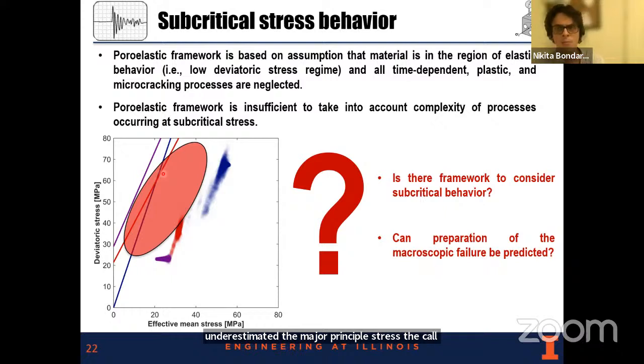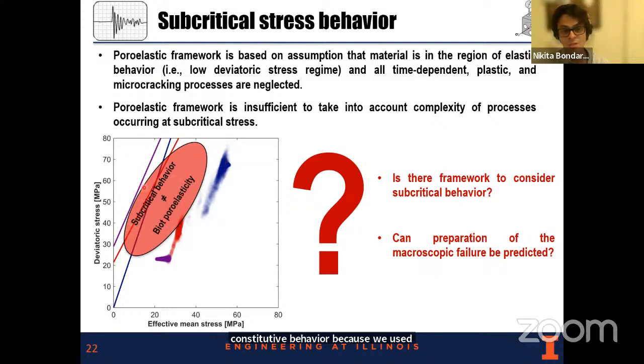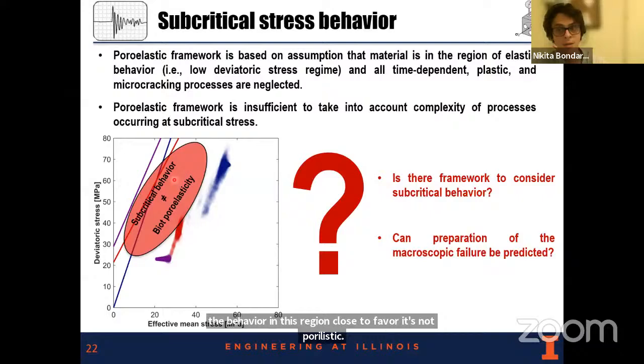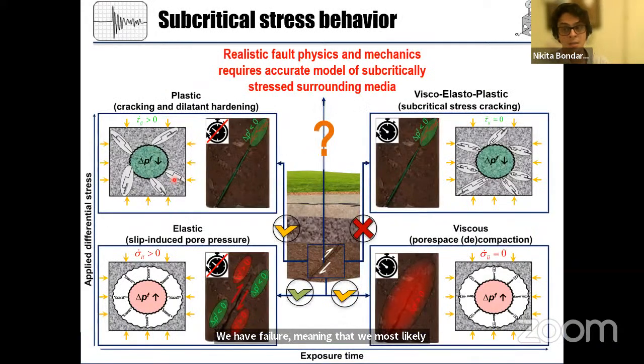At the same time, we can try to improve the constitutive behavior, because we used Biot poroelasticity to describe the constitutive behavior, while the behavior in this region close to failure is not poroelastic. We likely have some plastic effects and a time-dependent response. This is the domain of Biot poroelasticity: low applied differential stress and low exposure time.